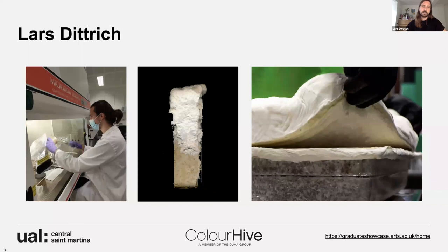And what happens is that the mycelium doesn't stay within the substrate. On the right, you can see a picture of the mycelium substrate in the plastic container. Through those growing conditions, the mycelium grows into a void space, because it's tricked into thinking that it's still on the ground, but really it forms this very thick mat of pure mycelium foam. And the quality of this foam can be quite different. You can get quite soft and squishy foams, but also dense and firm material characteristics. And one key element in growing this material is actually airflow.